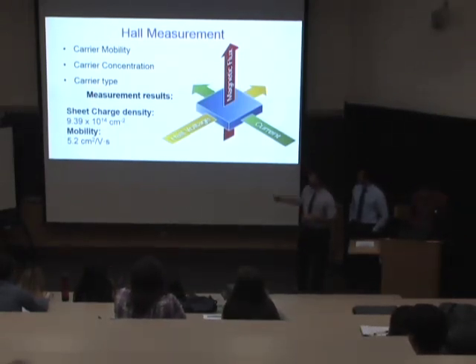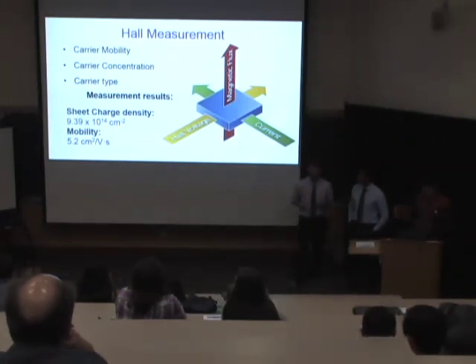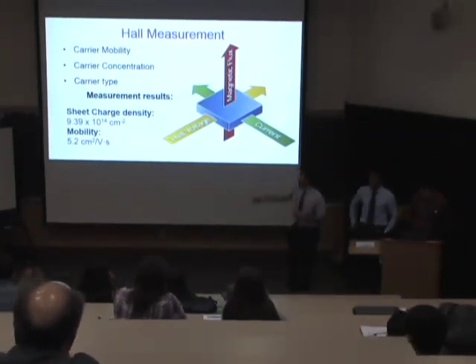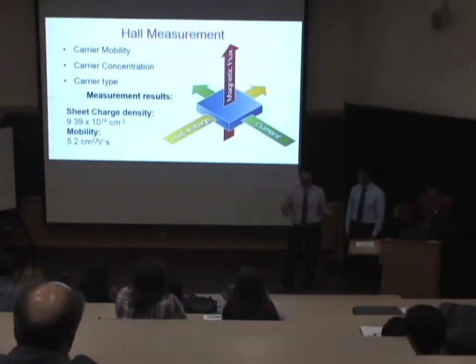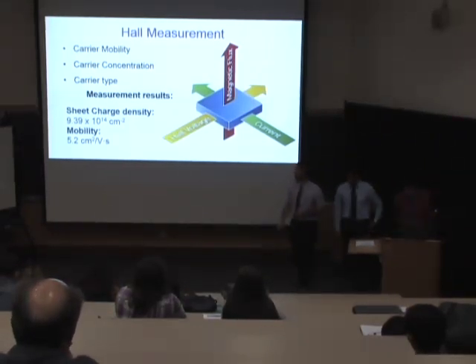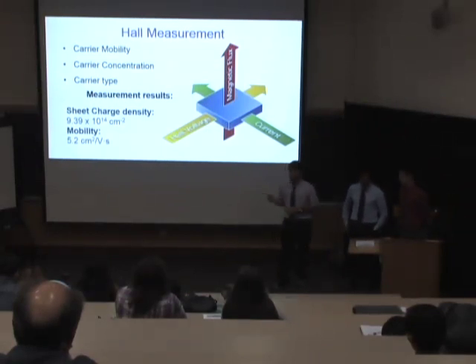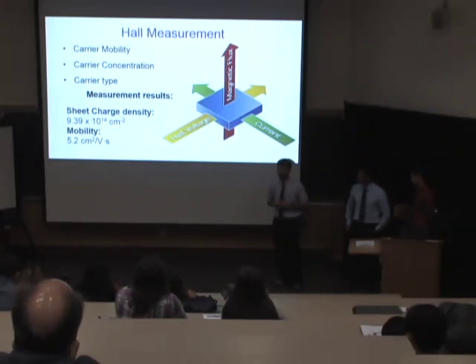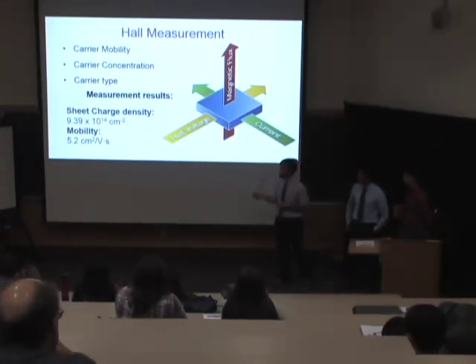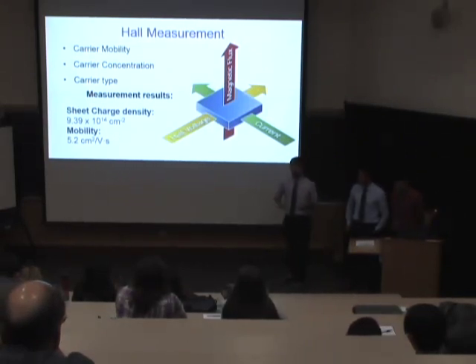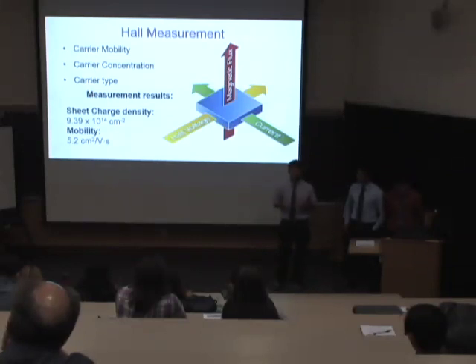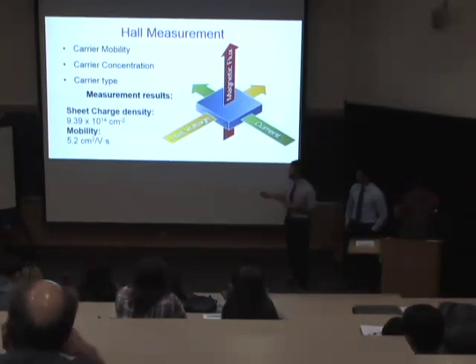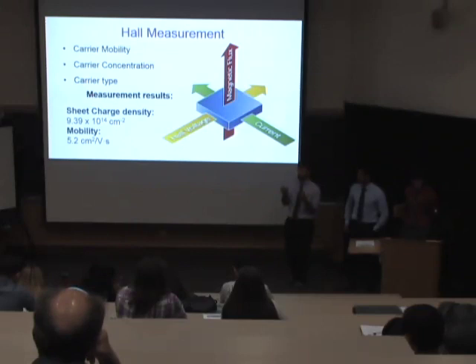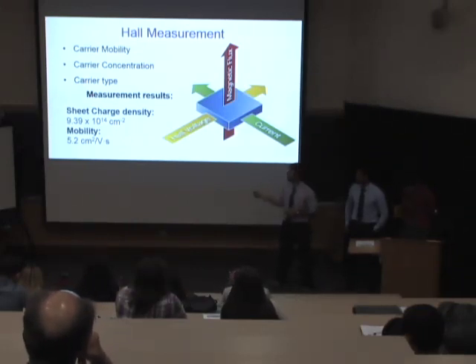Our measurement results, specifically for our oxide, which was STO, or strontium titanate, are here. You see the sheet charge density is 9.39 times 10 to the 14 per centimeter squared. We know that that number is very good. We were actually pleased to see that number. Our mobility is 5.2. This test was done at room temperature, but this same test done on STO at 2, 3, 4 Kelvin produced a mobility of around 30,000. That is far exceeding any current technology used. What we're hoping to do is take that same mobility found at that low temperature and bring it up to room temperature, where we are using our electronics.